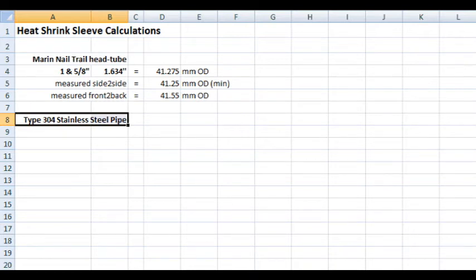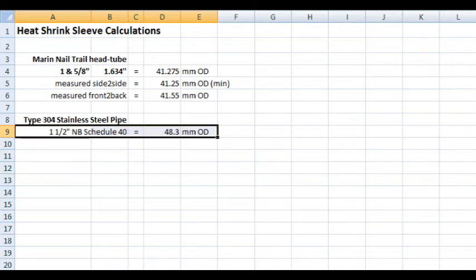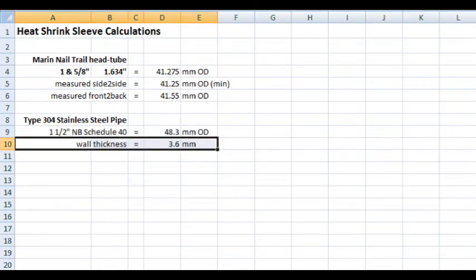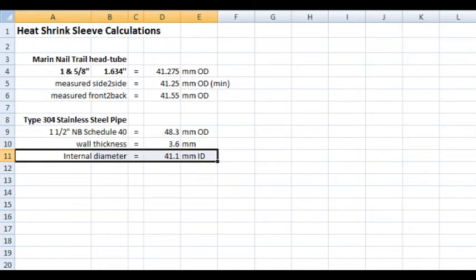I picked 1.5 inch schedule 40 tube that has a 48.3 millimeter OD and a 3.6 millimeter wall thickness. Now that's good, 3.6 millimeters, because it's similar to the thickness of the original head tube, so it's going to be strong. That means it ends up theoretically with an internal diameter of 41.1 millimeters, which, when it shrinks down, is still smaller than the smallest side to side measurement for my tube. So it's going to be tight on there, and that's what you're looking for.